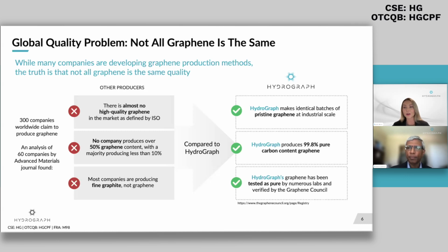These are really shocking figures, and really what this points to is that most companies are producing fine graphite, not graphene. And of course, most companies are using mechanical or chemical exfoliation with natural graphite to produce graphene, which of course takes a lot of energy to get down to that 1 atomic layer or very few atomic layers. Other companies also start with methane or other carbon-rich sources. But again, any other method is endothermic, energy is put into the system, as opposed to HydroGraph's exothermic process, where we are giving off energy.